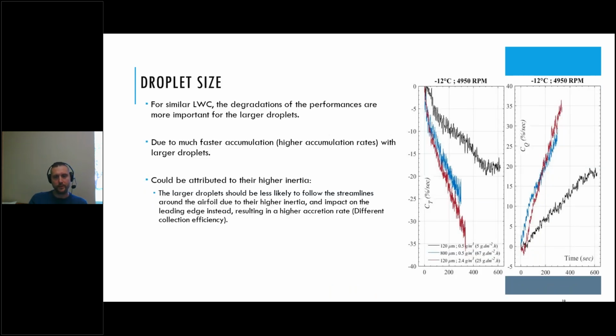So the first parameter that we looked at was the effect of the droplet size. We observed that the degradation of the performances was far more important for the larger droplets. As you can see on those plots here, with the black line showing the droplets of 120 microns compared to the blue line, which showed the 800 microns, you can see a much faster degradation.